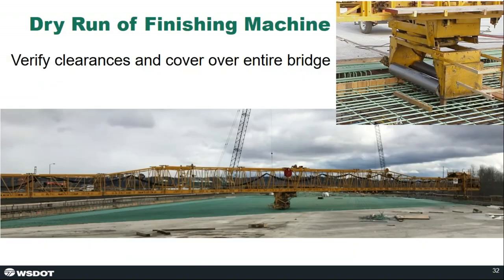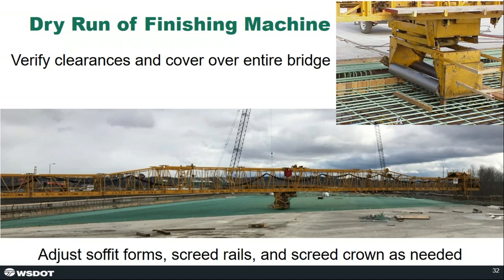Once the rebar is in place, we go through a dry run with our finishing machine. So the finishing machine is operated over the entire bridge deck area, and we're measuring for clearances and cover, specifically that 2.5 inch clear cover over the top mat of steel. This is where all the geometry has to come together in the construction process. The photo on the bottom there shows a truss that's over 100 feet in length supporting a finishing machine. So there's a lot of factors in play here.